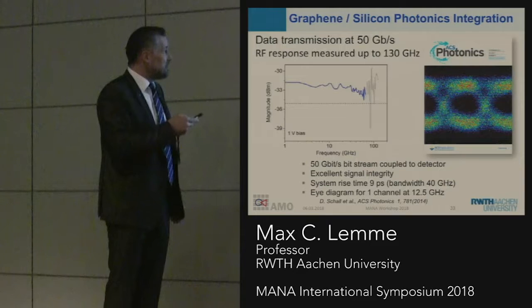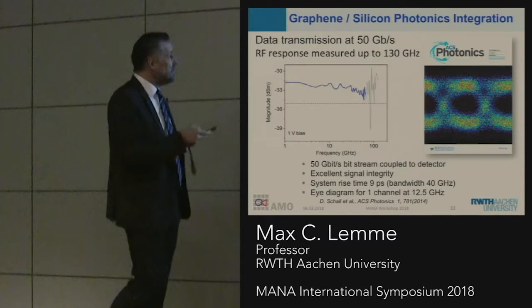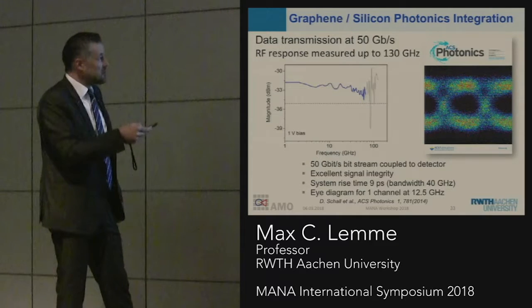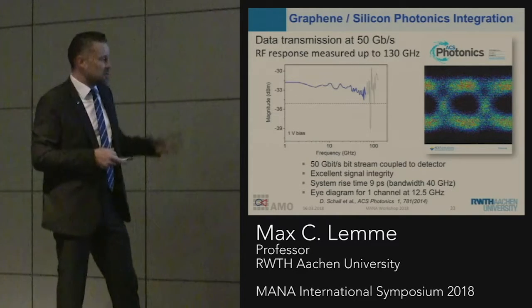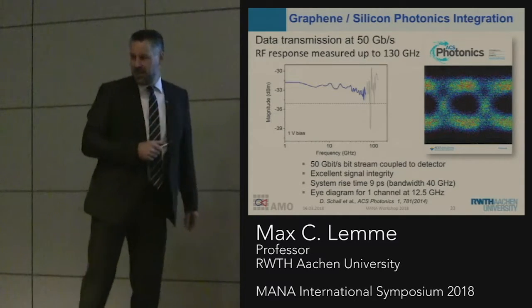This measurement is the RF response measured up to 130 gigahertz. We show data transmission at 50 gigabits per second. So these numbers are quite good.